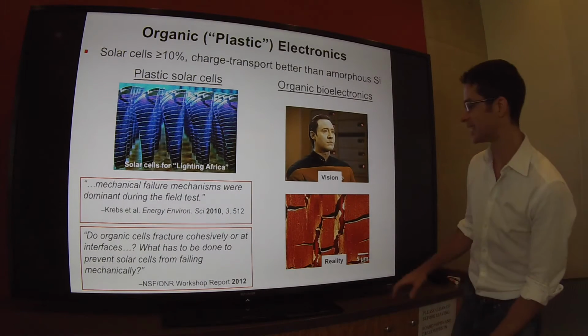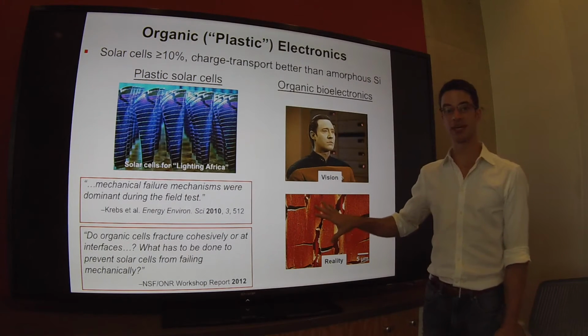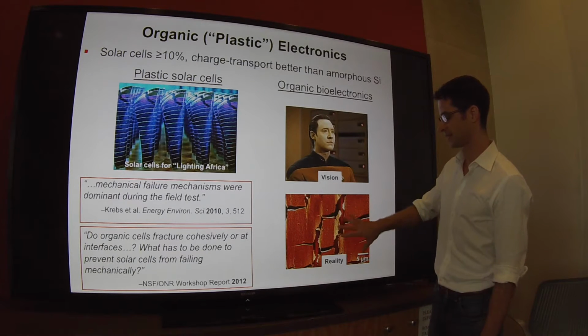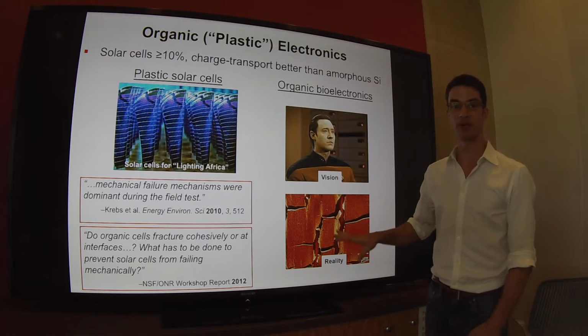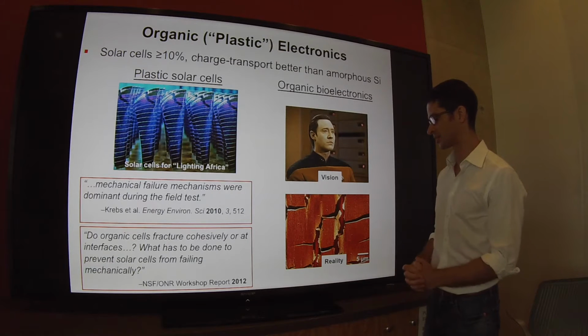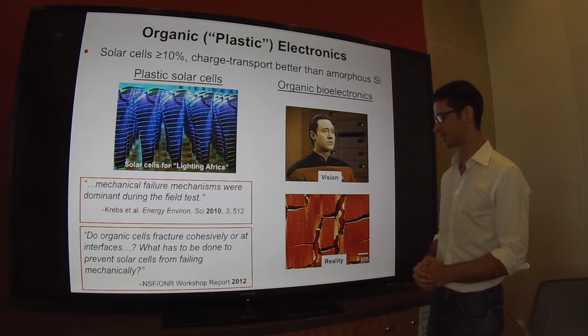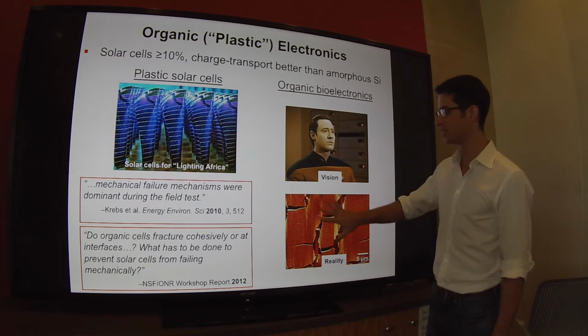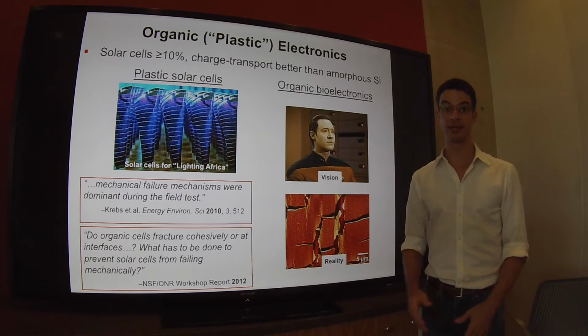Now the problem is, again, if you zoom in to the surface of the organic semiconductor, this is an atomic force micrograph of an organic semiconductor. This is a P3HT:PCBM blend at 20% strain. You can see significant mechanical failure.